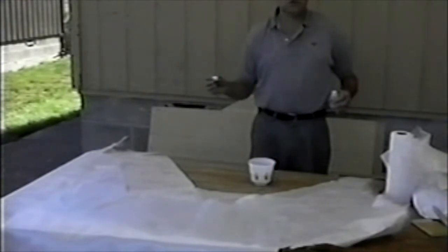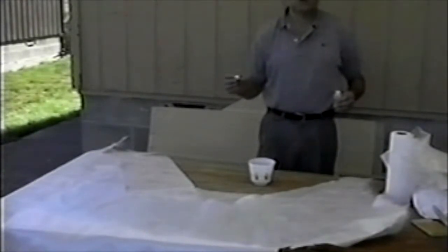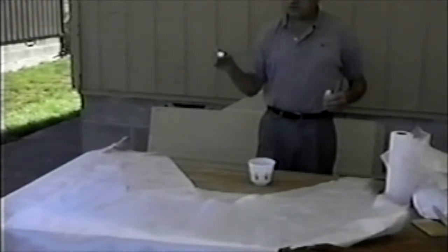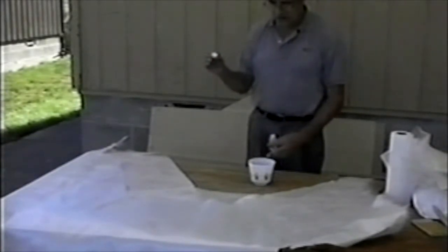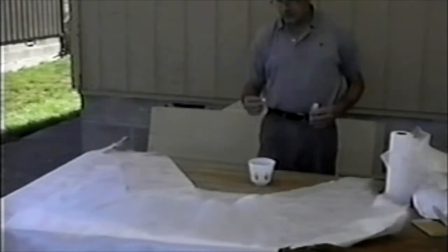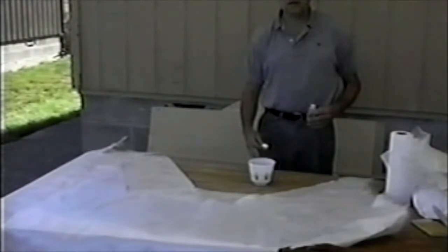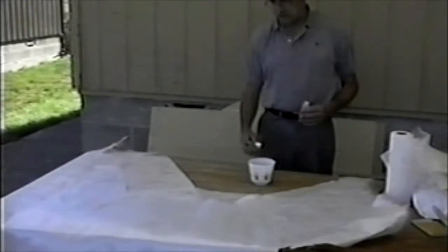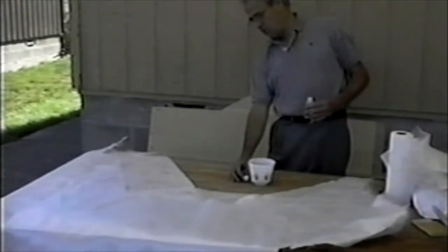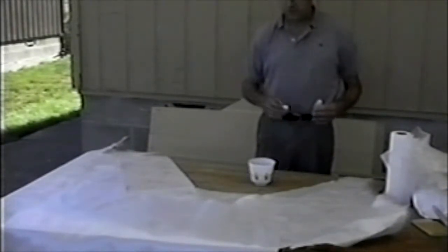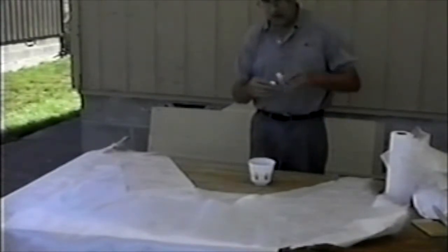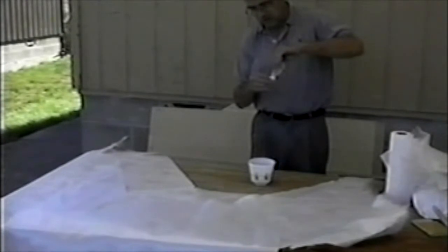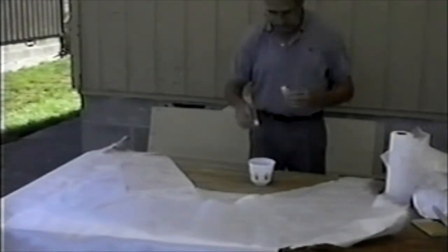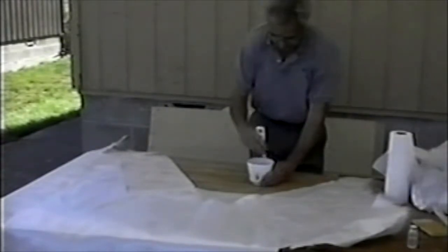And the surface area is the square of that, or it's 25 times the surface area. Or turning the numbers over, this cap has about 4% of the area of that surface. If I filled this cap to the same depth as the resin in the can, I would have 4% catalyst. So I can see the cap is only about 1/4 as high as the amount. So one capful will give me about 1%, and we'll try 1% catalysis for the start. So I fill up the cap with the catalyst and dump it in. The resin is rather non-critical as far as stirring goes.